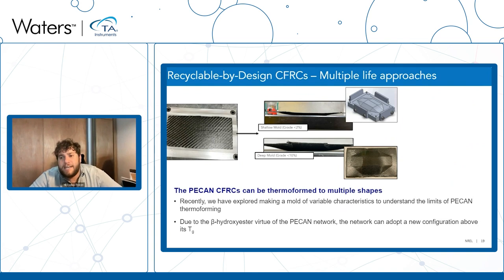Also, John gave a great preamble to this talk. These epoxy anhydride chemistries, or these polyester covalently adaptable networks, can rearrange their network topology. So we can also take our CFRC panels, which are flat panels, and we can thermoform them into different shapes. Here we made this wonderful prototypical part that has a bunch of different geometries, and we can thermoform our material into a bunch of different shapes by virtue of this covalently adaptable network, which is really valuable for the vehicles industry where you're trying to make cars of different shapes and sizes. So we've shown that we can press this material into multiple shapes themselves.